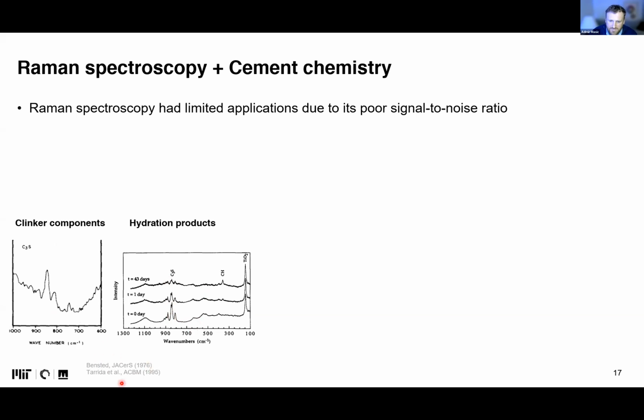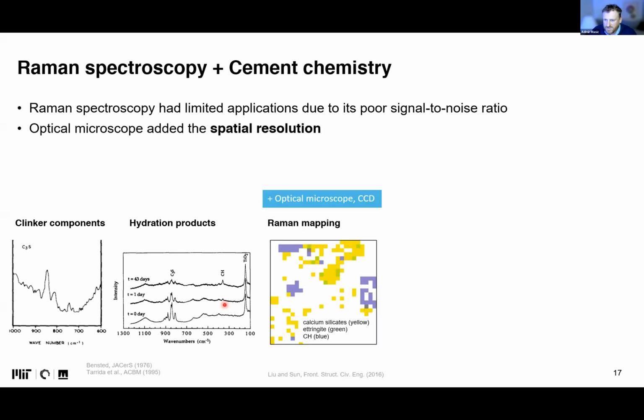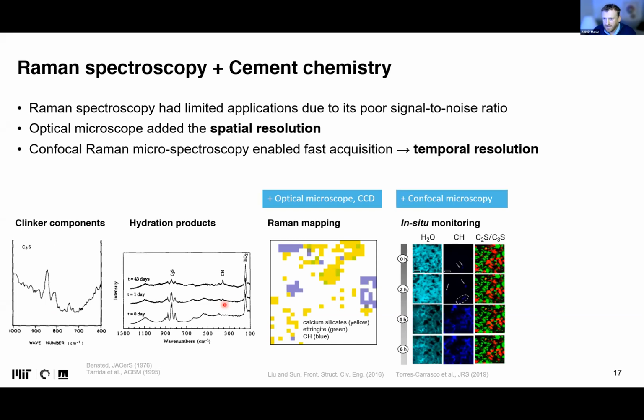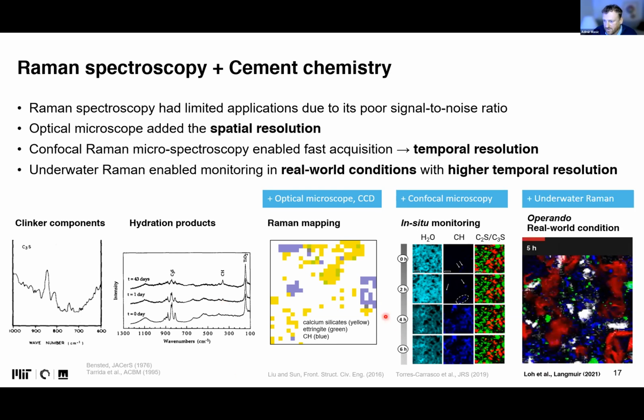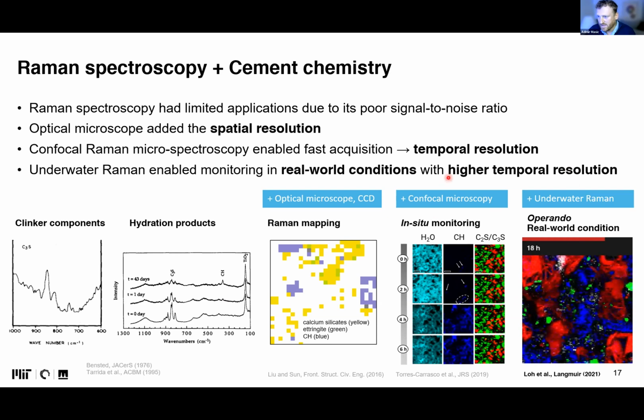Quite challenging experiments done in the 70s and 90s. But then with optical microscope integration, and especially with confocal microscopy, we were able to focus this laser to a very small volume, with a limited amount of trace metal elements or other sources of fluorescence, and eventually we were able to get this. We are talking about 2019 and 2021, so very recent work. The cool thing about this most recent paper is that we do it in underwater conditions, meaning that the processes occur very similarly to real-world conditions. So we call it operando.